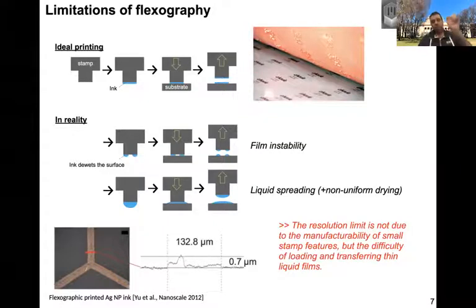And in reality, when you try to make the features smaller, you run into issues such as film instabilities on the stamp. If you're trying to load a very small amount of ink, i.e. a thin layer, the ink can de-wet. Or if you want to get good contact between the stamp and the substrate, you squeeze out ink due to excessive spreading. And that is compounded by non-uniform drying. So the limit to the scale and resolution of flexography as a printing process is not the stamp features themselves. You can cast and mold polymers to sub-nanometer scales, but it is the difficulty of loading and transferring thin liquid films.